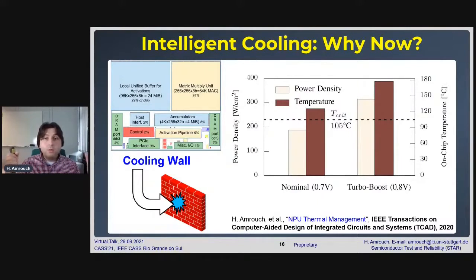And no surprise, because it can even reach 180 degrees. There's no surprise of that if we look at the power density, the total power consumption of those 64,000 MAC units. And remember, a multiplier is always very power hungry. If you put 64,000 of those multipliers working simultaneously, jointly, generating huge power confined in a very small area, 24% of the entire chip, then the power density can easily reach 200 watts per square centimeter and even nearly 300 watts per square centimeter if you boost your voltage.